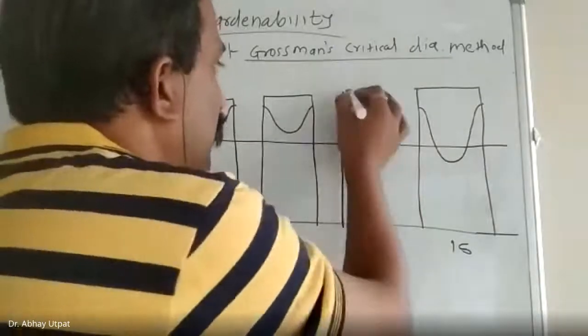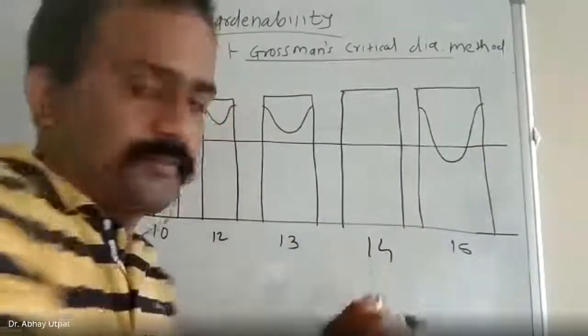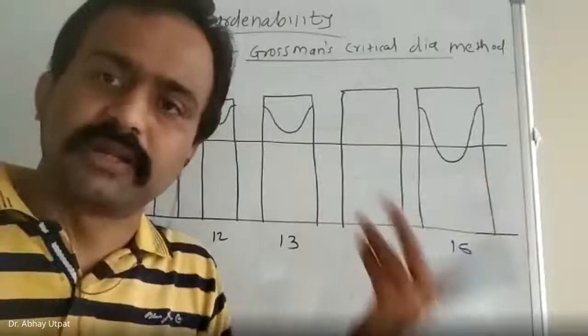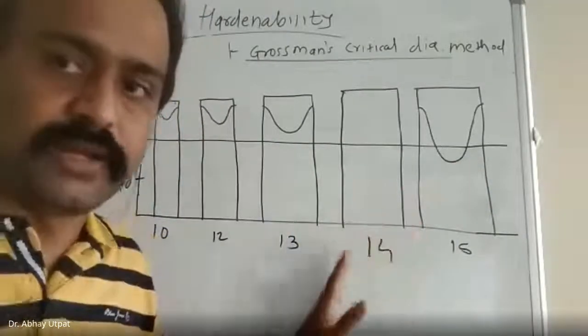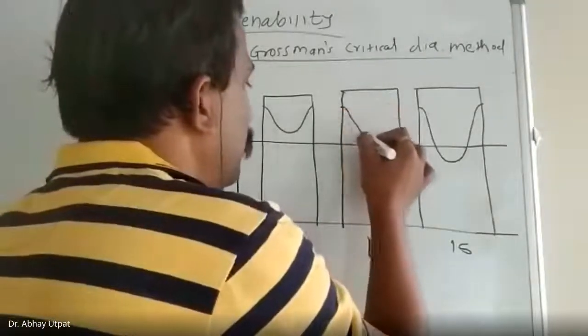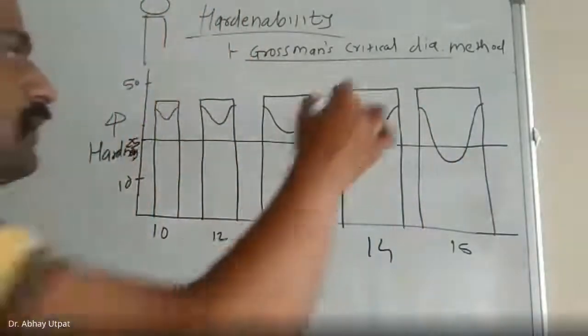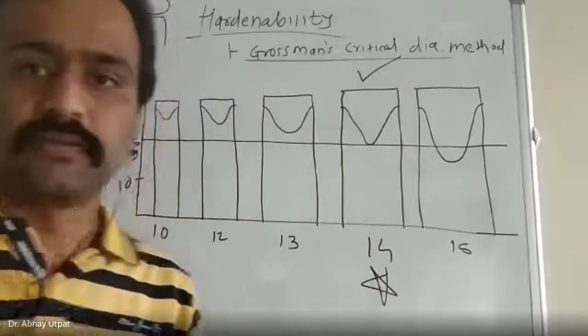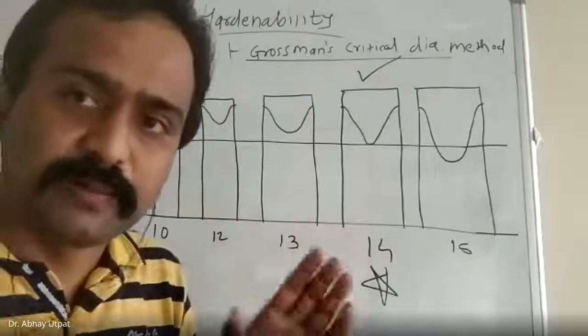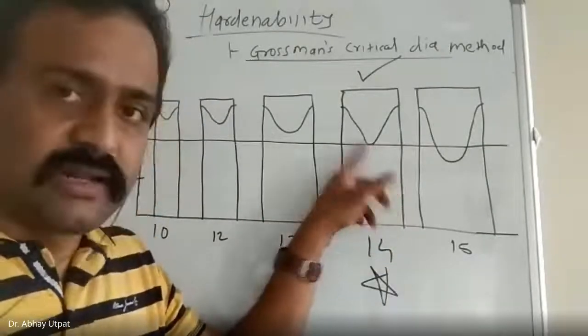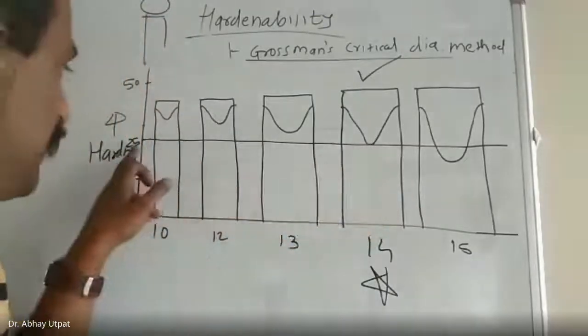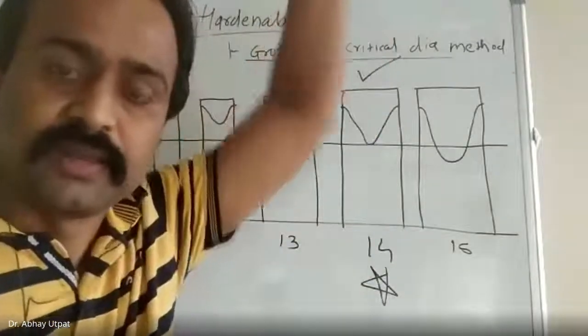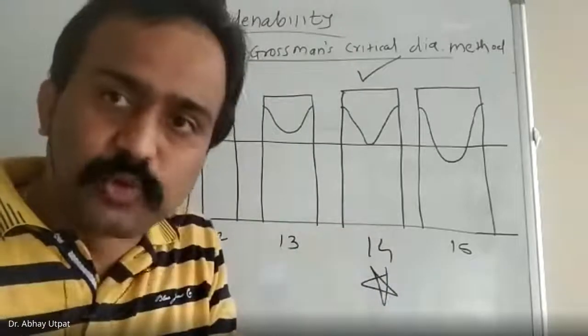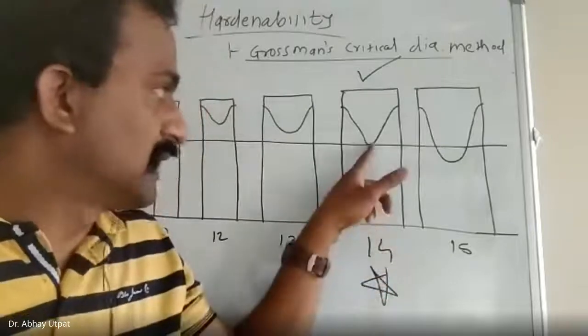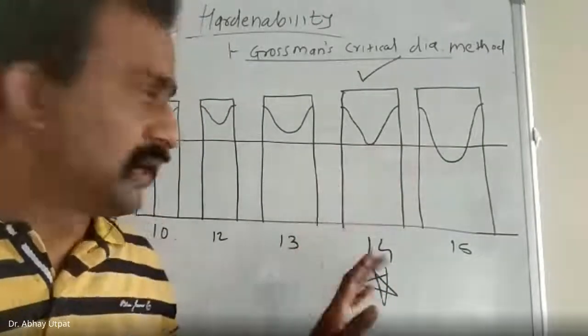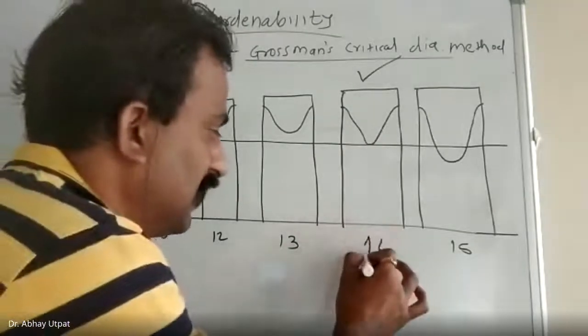Actually, it may not be exactly 14, but for easy understanding, I have taken 14 mm. It may not be a round figure. It may be 14.2, it may be 13.9, anything. But for your understanding, I have taken a round figure. And for 14, I got this graph. What is the specialty? This is a 14 mm diameter bar, which gives a correct hardness value of 25 at the center. This hardness of 25 corresponds to 50% martensite. That record I am having. It means without checking this sample under the microscope, I can say that for this bar there is 50% martensite at the center. And now this 14 is my critical diameter.